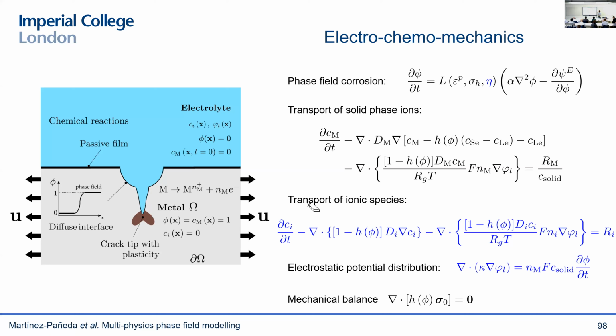We can also add all the electrochemistry. So again, you have the phase field for the corrosion problem. You may have a phase field of the fracture. You have the transport of solid ions, but then you also have this transport of ionic species.